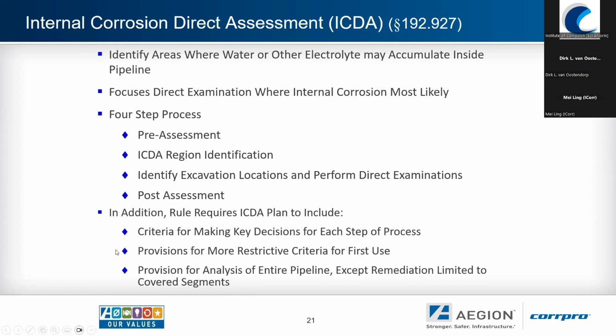So one of them is, for the very first time that one applies the internal corrosion direct assessment process, the criteria is a little bit more restrictive as far as demonstrating the applicability. It's going to take into consideration the analysis is done on the entire pipeline, but the remediation is only limited to the covered segments. And in this case, the point there is the regulations focused in on what are called high consequence areas along the pipeline, which have set criteria published by the Department of Transportation. So even though you are assessing the entire pipeline, from the regulatory standpoint, you're only required to focus in most heavily on these areas that are high consequence.